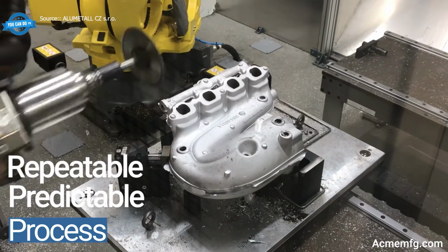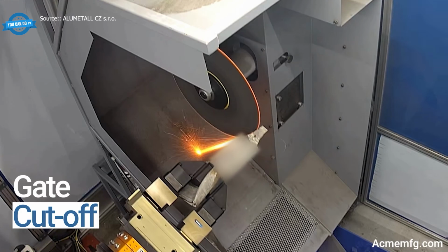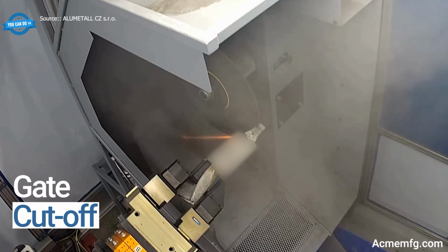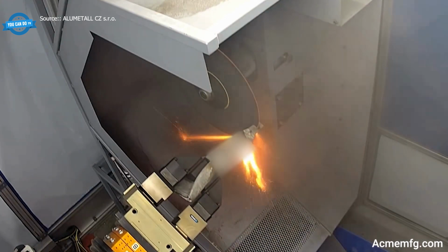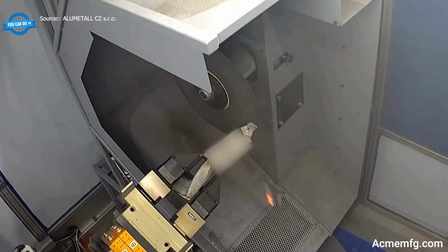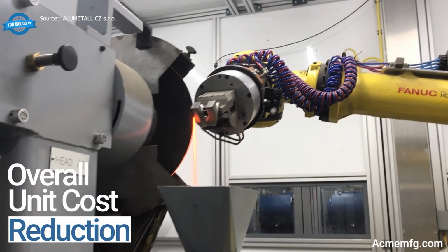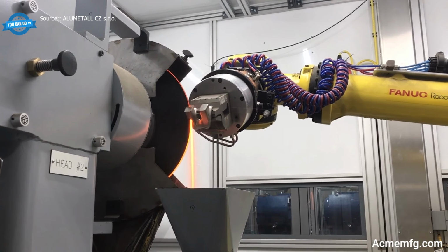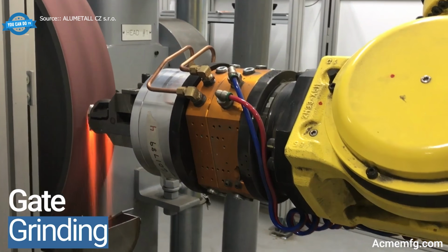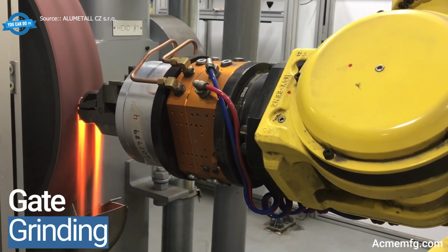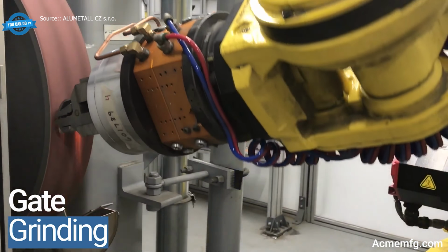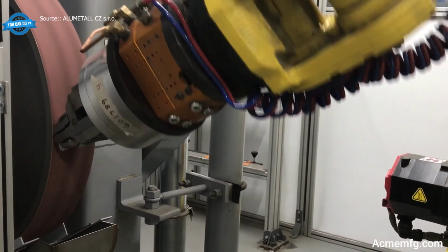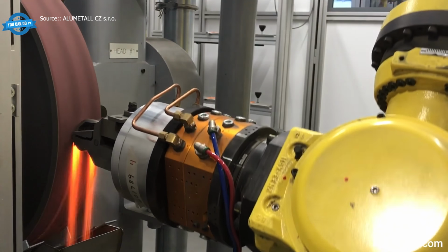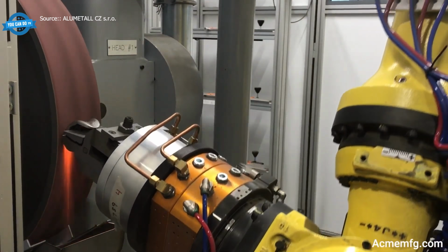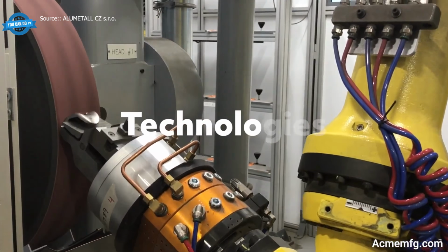Robotic grinding cells have quietly taken over the worst of it. A 6-axis arm with a diamond wheel handles gate cutoff, flash removal, and surface grinding at a pace no human worker could keep up for more than a few days without an injury. Abrasive media life management tracks how worn the wheels are and swaps them before a bad grind ruins a good casting. Scrap rates drop, part yield goes up, and nobody has to breathe silica dust for a living anymore.